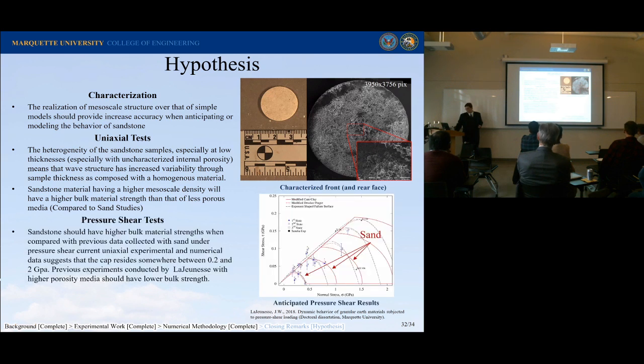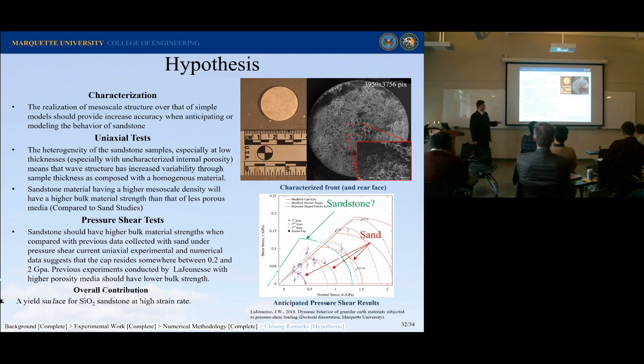Finally, I want to do these pressure shear tests. So I'm thinking that sandstone should have a higher bulk material strength when compared to previous data collected for sand. So this is the high strain rate data for sand. And if I do my tests, I'm hoping that my sandstone curve will fall above the yield surface for the sand. So I'm hoping, as from before, remember when we had the sand and the sandstone at low strain rate, I'm hoping now at higher strain rate, we get the same behavior, just at higher strengths than low strain rate.